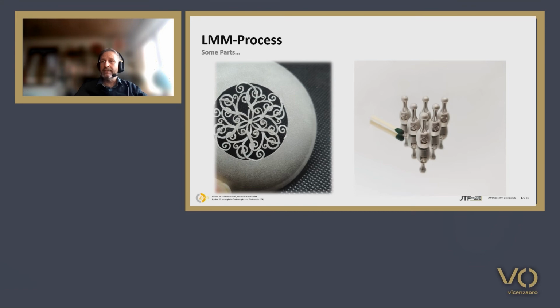And if you don't do that, it will sinter together with the rest. So this should have been cleaned better, and this could have been done with a kind of airbrush gun with a very mild spray of material. The second part that was made was cleaned much better. Again, you see some printing lines, and this is because the whole thing has an oval shape, a very large radius over it. So this has to be after-treated with some hand polishing.